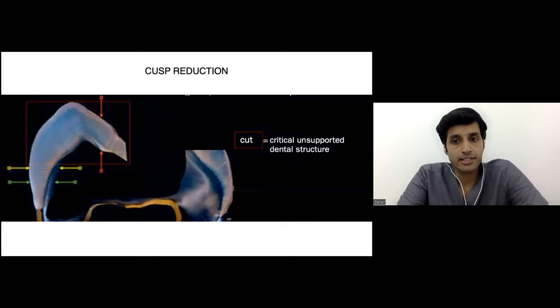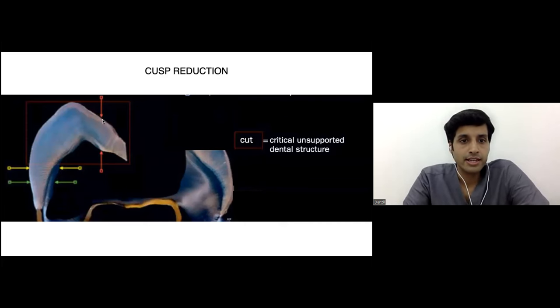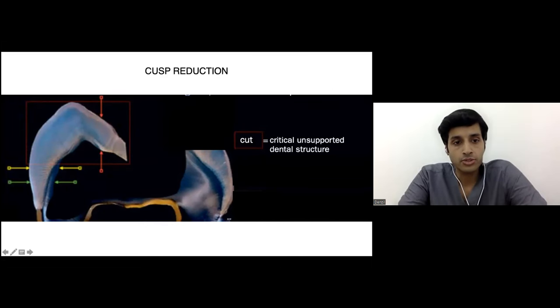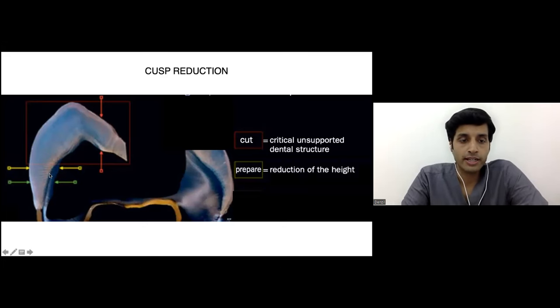And here you can see there is unsupported enamel. So in this case, the outline of the red box is what the enamel should be cut short to. And what do we do of the remaining? Now, this is also unsupported, pretty much till this level. But we also have to preserve enamel. So in that case, we reduce the height, the yellow markings, and all the green areas, this undermined dentine, will be filled with composite. This entire area will be filled with composite, and this part will be preserved.